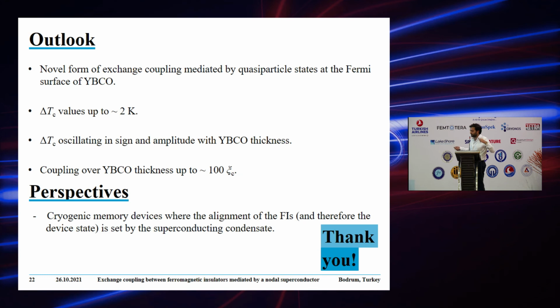despite the fact that the superconductor is much thicker than the coherence length along the z-axis, because you have the existence of these quasi-particle states for which the coherence length effectively increases, because the coherence length in a nodal superconductor is inversely proportional to delta, and delta becomes close to 0 near the nodes. The delta Tc values are up to 2 Kelvin, and then you have a change in delta Tc as well, depending on the thickness of the superconductors.